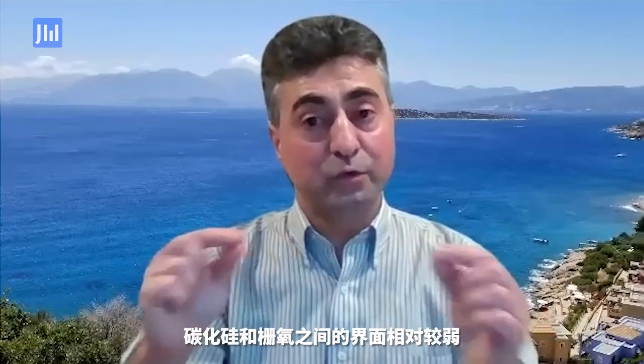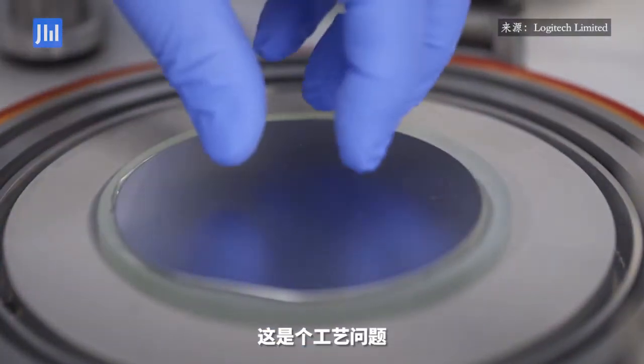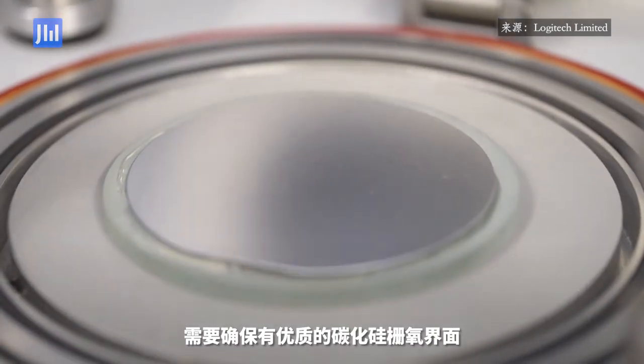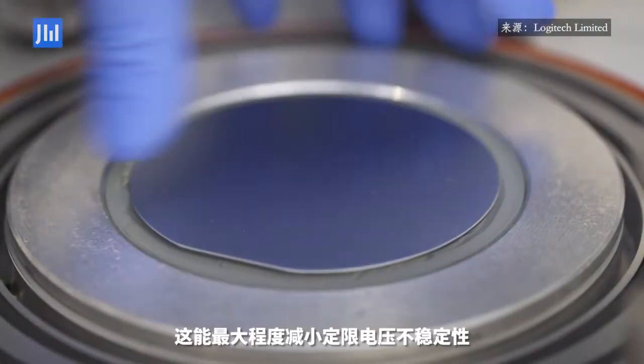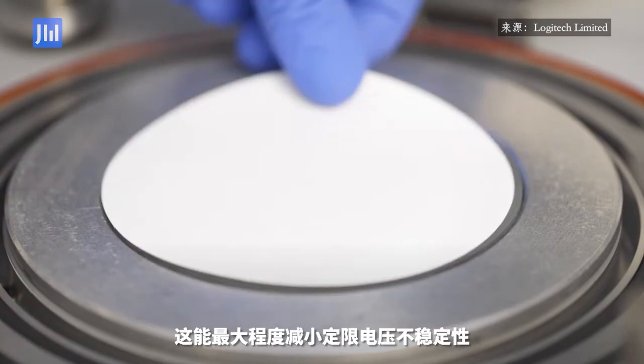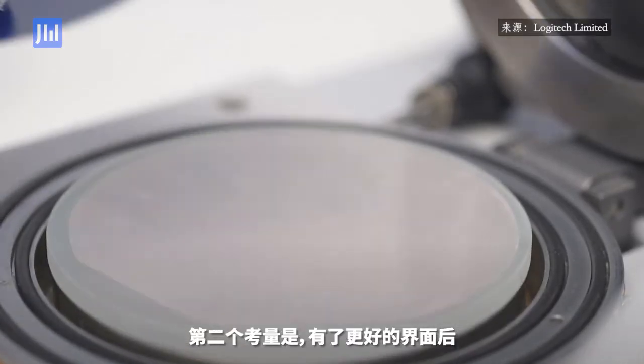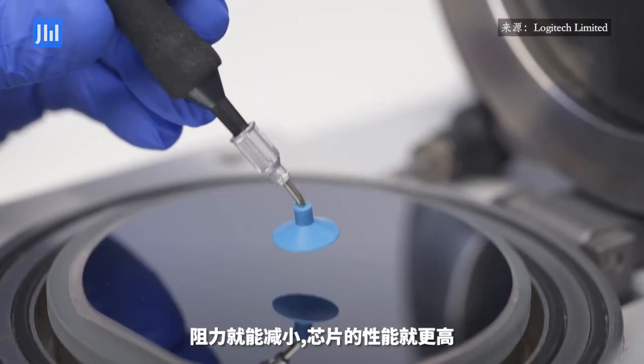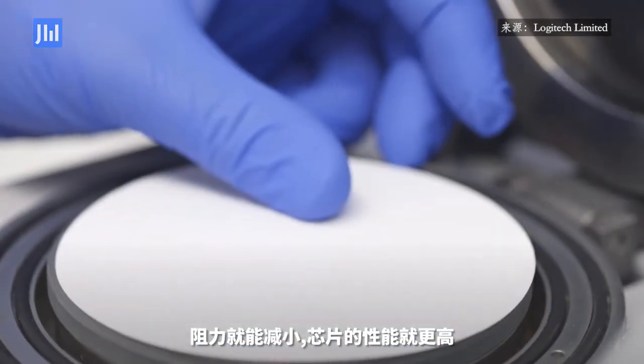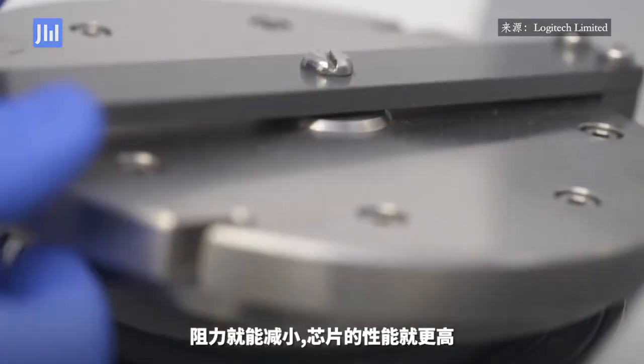The interface between the silicon carbide and the gate oxide is relatively poor. It's got a lot of interface traps. That is a processing issue. You want to make sure you have a very good silicon carbide and oxide interface. It will minimize or eliminate the threshold voltage instability, which is a reliability concern, number one. Number two, if you get a better interface, then your resistance will go down. You will have higher performance devices.